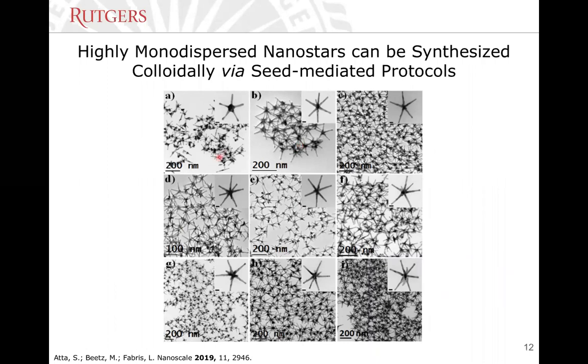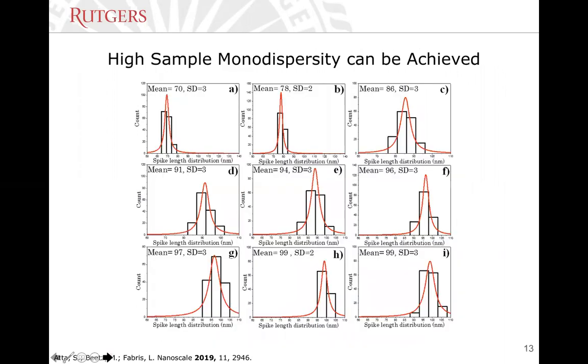Not only that, what we saw is that if we increase the amount of silver nitrate, not only can we tune the length of the spikes, but we can maintain monodispersity. Now it's kind of difficult to see in these slides, but looking at these bar diagrams, we can see that the distributions are very narrow with standard deviations of about 2-3% or even lower in some instances. This is very interesting because yes, these particles are not yet perfect, but achieving this monodispersity is very difficult when you have high shape anisotropy and these very, very anisotropic shapes, right? There is one question though that we keep asking ourselves: what is monodispersity in this case?